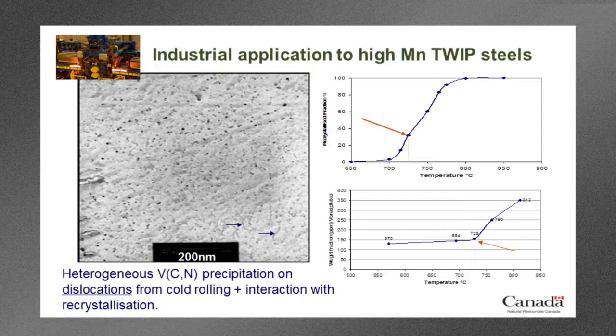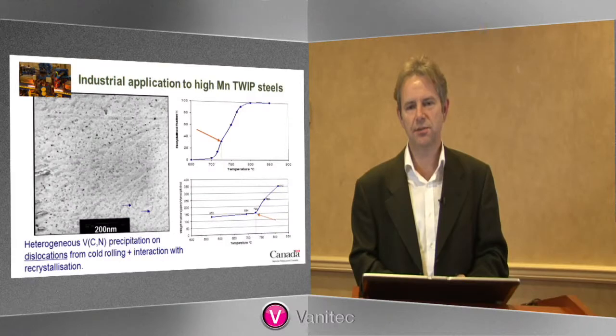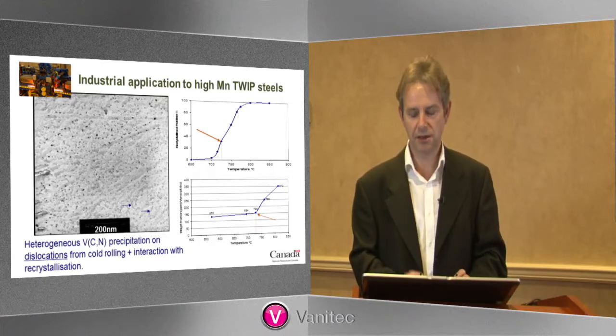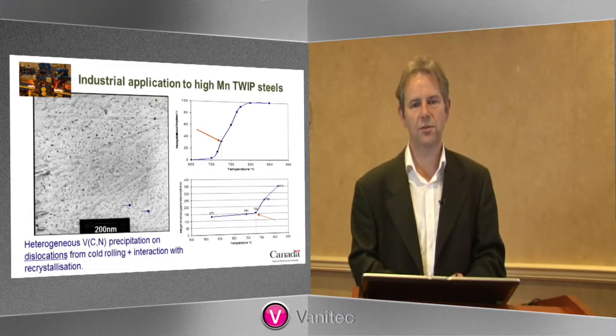So that means this is when the vanadium carbonitride precipitates really start to nucleate. And this goes up here. And if we went into this curve, it would keep going as we go into the isothermal part of the recrystallization annealing step. At that same temperature, 725, you can see there's a kink, a slowing down of the recrystallization kinetics. So it means that there's an interaction between these precipitates and the recrystallization behavior of the material.